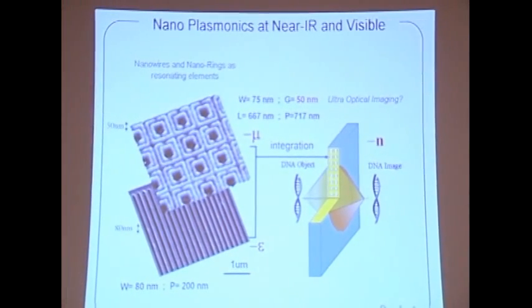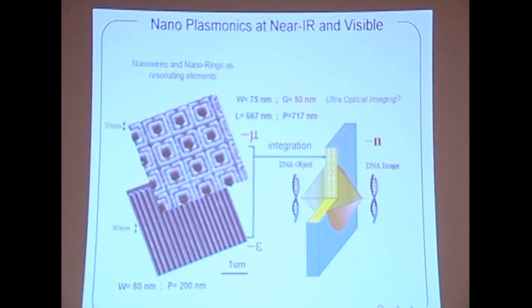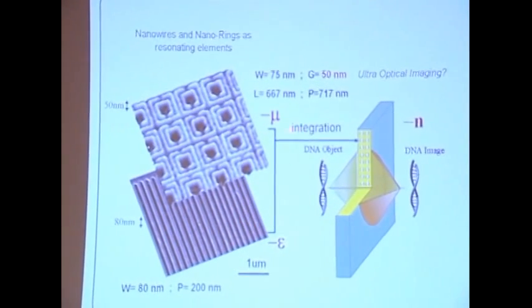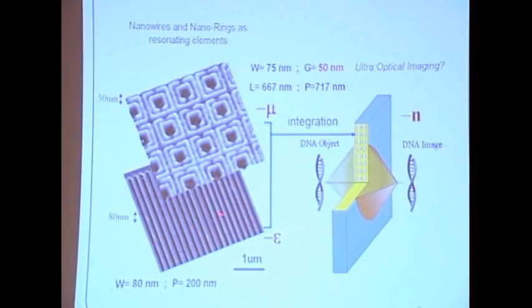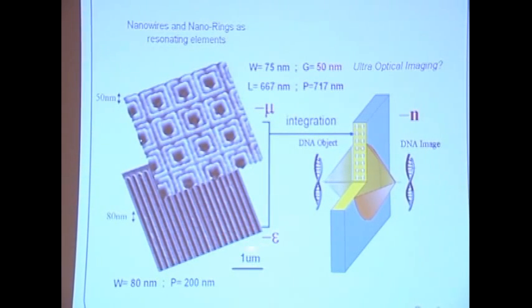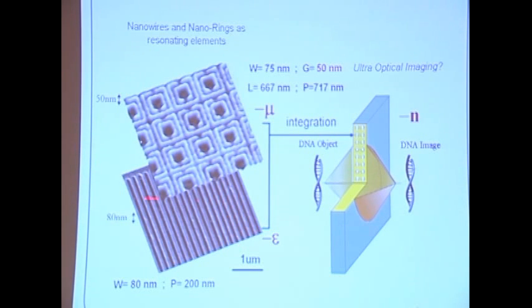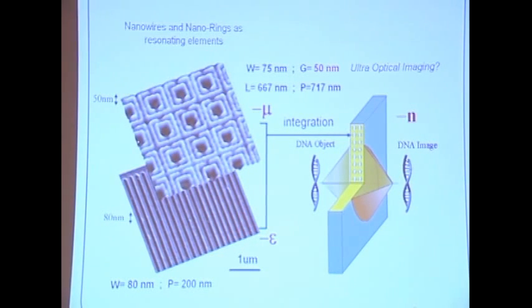So if we can really push the magnetic response to a high frequency, such as infrared or optical, and we can engineer this magnetic response to be not only positive but negative. And also, I don't have time to talk about the electric response on the plasmonic part, but generally using nanowires, you can introduce the plasmonic response. That gives you the possibility of easily negative epsilon. By combining the mu and epsilon, both negative, causality requires that the index of this medium, if you use this piece of things to construct a medium, has to be negative.